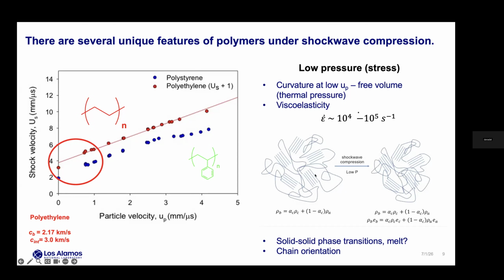And my little spaghetti diagrams are shown at the bottom. So if you think about compressing these structures, I show here schematically the crystalline domains by the ordered sections, and the spaghetti linking them all is the amorphous domains. So a big question we had was, when you compress this structure, how is that compression energy distributed between those two different domains? You might expect that the amorphous domain would take up a lot of the free volume compressing out first. And when thinking of it from the high pressure community and the diamond anvil cell community, you might actually think that the amorphous domains might act like a hydrostatic medium around the crystalline domains.